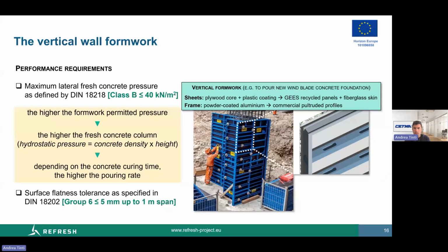Vertical formwork has specific standards to comply with, defining the most important performance parameters, most of all the so-called maximum lateral fresh concrete pressure, which in turn reflects the maximum height of the fresh concrete column, and the surface flatness tolerance under pressure in order to avoid a rounded structure. For both parameters, the target values we aim for are highlighted in this slide.